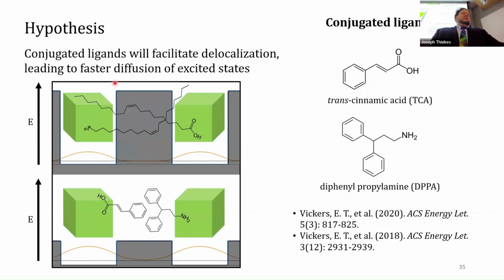And so we had this thought that maybe the conjugated ligands can facilitate delocalization of the excited state and lead to faster diffusion of excited states through the array of nanocrystals. This diagram here is like the particle in a box toy system. You've got your wave function, and it's isolated by this barrier, which is just the space between the nanocrystals. And these aliphatic ligands are not going to help to move any energy around. But our hypothesis is that if we use these ones, we've got conjugation and these aromatic rings, we may be able to delocalize the excited state and lower those barriers to transport.